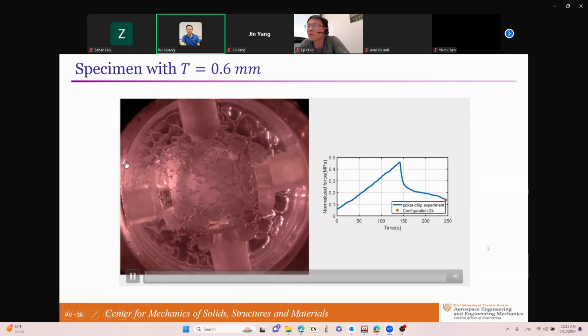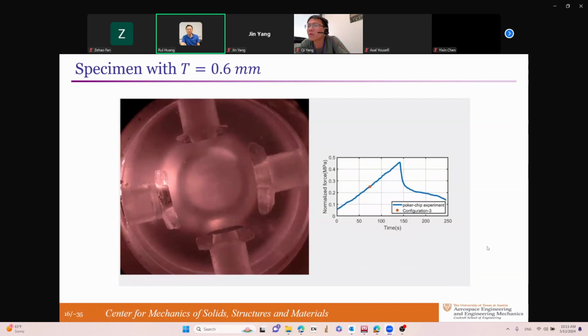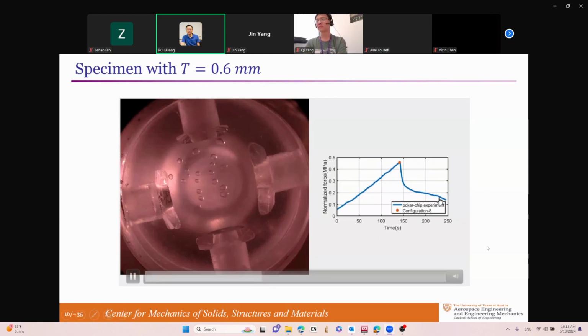And it's completely dominated by nucleation. They don't grow, they're unable to extract energy from the neighborhood. And they continue to nucleate until the entire surface or the cross-section is filled with nucleated cracks. The deformation then continues to increase, with rupture at some later stage, way beyond where I've shown you the videos.